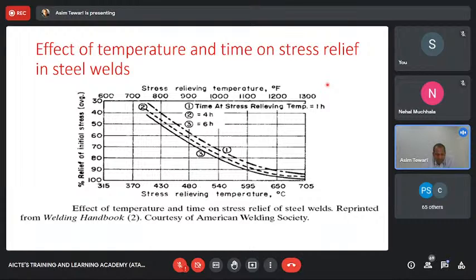And there are many mechanisms involved in there. Plasticity is one. Why? Because when you heat it up, the plasticity of the material falls down, the yield stress falls down. Another mechanism is creep, in which the material starts flowing because of creep. You also have stress relieving because of dislocation movements. Your dislocation mobility increases. So a lot of things happen which lead to reduction in residual stresses when you expose something at a high enough temperature for a long enough time.